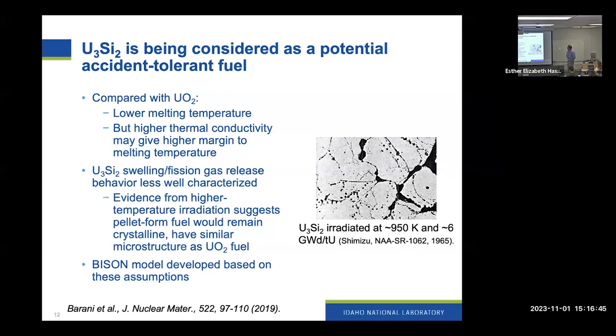U3Si2 fuel has been used in research reactors in the past, but in a commercial reactor, where it would be operating at a higher temperature, the evidence that's out there suggests that the microstructure would be very similar to what's seen in UO2: fission gas bubble growth, interconnection, and release. And so some colleagues a few years ago developed a model in Bison based on those assumptions.